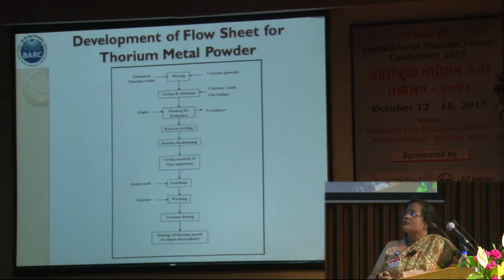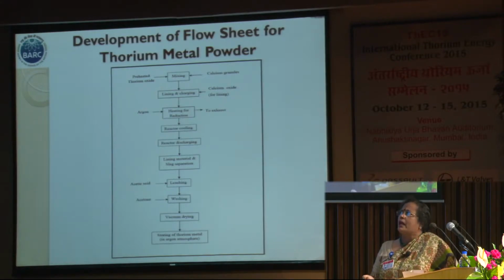Based on this, we started working on a preparation method for thorium metal, and we developed this process for calciothermic reduction of thoria to get thorium metal powder. This process was earlier also tried at AFD, and they mastered part of the issues, but presently they are not doing it, so it was revived by our division.